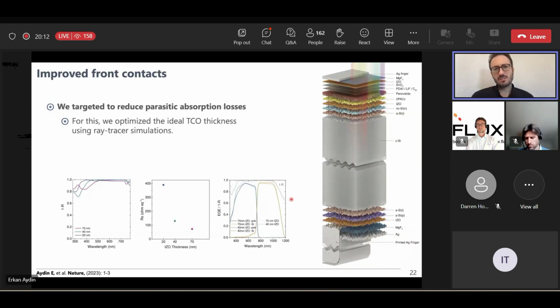We did a similar strategy at the front side, because the light is coming from the front side. Definitely, any parasitic losses will cost us current. So here, one of the biggest contributions was coming from the front TCO, and we did the thickness optimization by doing a power loss analysis. Then we found that if you use 40 nanometers, we match the current density of the subcells nicely, and also minimize the absorption losses, especially in the deep blue part.